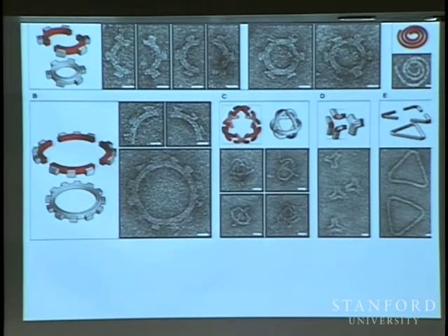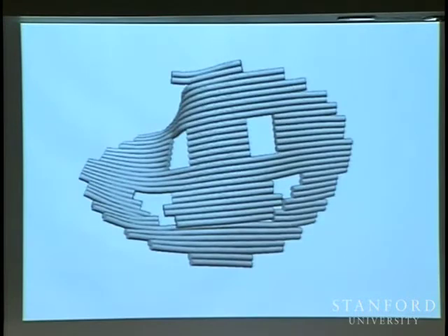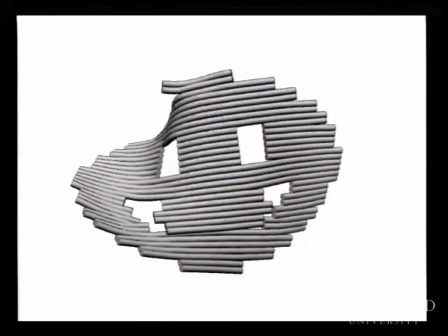Now getting back to your question about whether or not things are flat, so if you take my original model for how I made the DNA origami structures, I said I thought I made them flat, right? It turns out if you use the best model that we have derived from the parameters that you extract from this kind of work, and you revisit the smiley face, it looks like that in solution, right? So the smiley face is in fact probably not flat, and we know that many of the other structures I've made, we have direct evidence, you can see that they're not flat. It gives you terrible results when you try and fabricate something out of them.